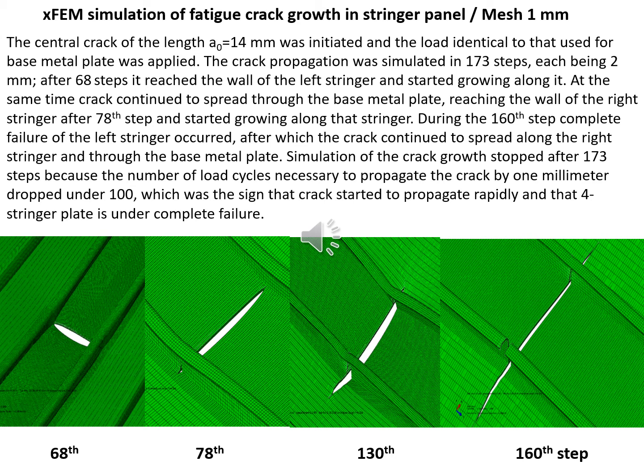Now we can focus on a crack path. This is the most important issue here. You can see one of the meshes, the one with the most refined elements, just 1 millimeter in size. Initial crack length was 14 millimeter. It was central crack as shown previously, and up to 173 steps were simulated. You can see that crack propagated up to 68 steps to reach the stringer, both left and right. Some asymmetry has appeared, but almost symmetrical problem, as it should be.